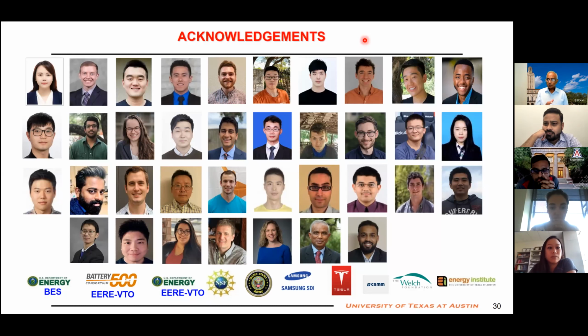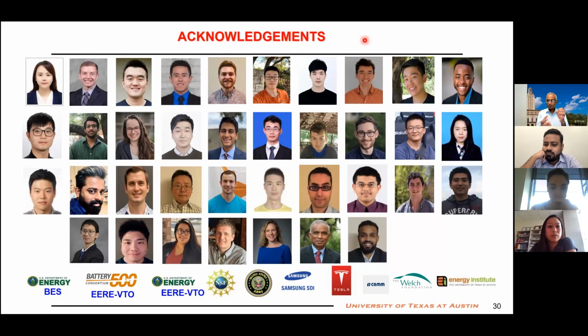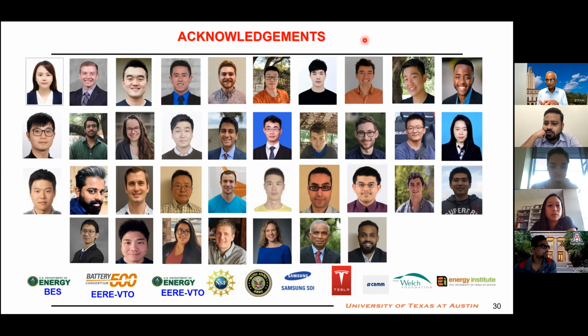There are people who attribute the high nickel completely to the crack. It is not, actually. Crack is not the biggest problem. The biggest problem is high nickel surface reacting with the liquid electrolyte, and then things are getting dissolved. That is the major problem, because nickel 3+ and nickel 4+ is not stable in contact with the liquid electrolyte. That is the biggest problem.